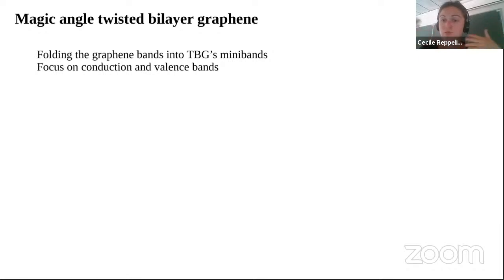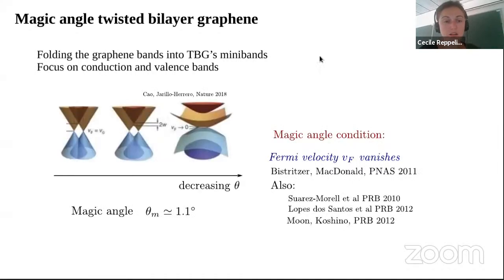Thanks to the tunneling between the top and bottom layers, there are gaps that are opened, and conduction and valence bands are separated by a gap from lower and higher bands. So you know the usual story: as you go to very small angle, you flatten the band very much until you reach a magic angle of around 1.1 degrees. And then if you keep going down, the bandwidth will start increasing again. So we'll stop at the first magic angle.